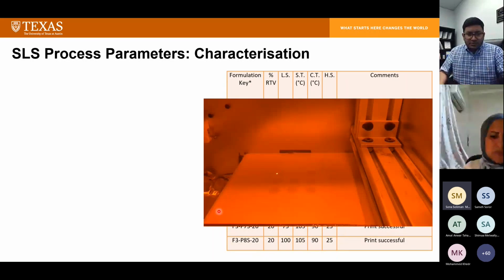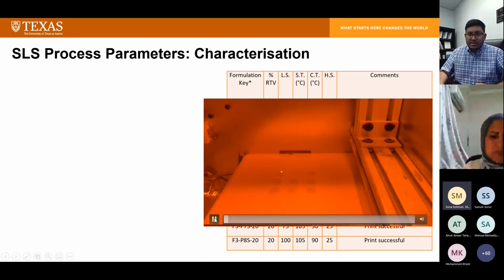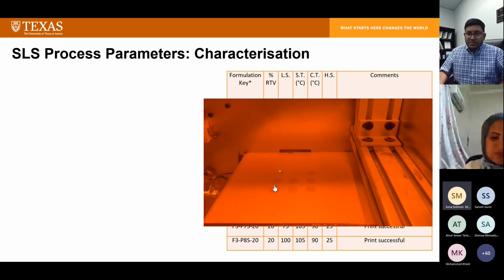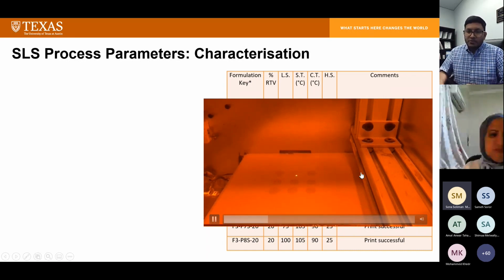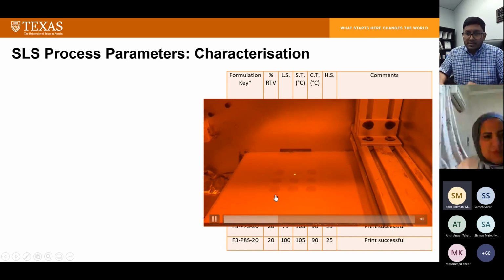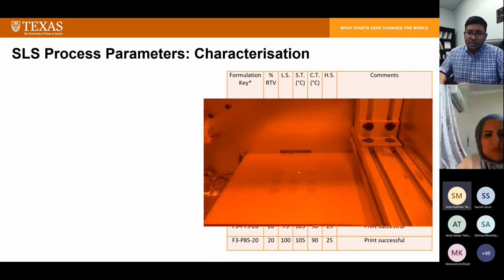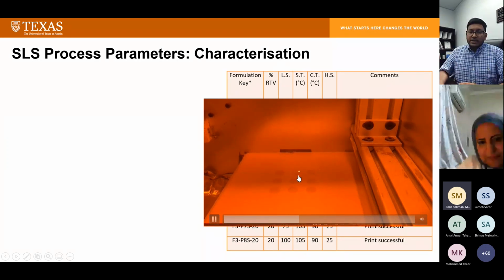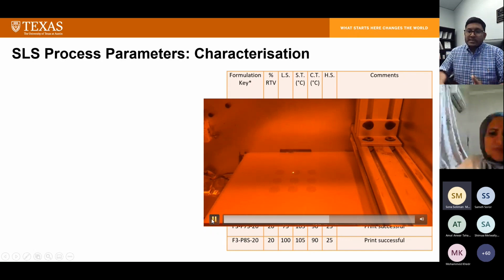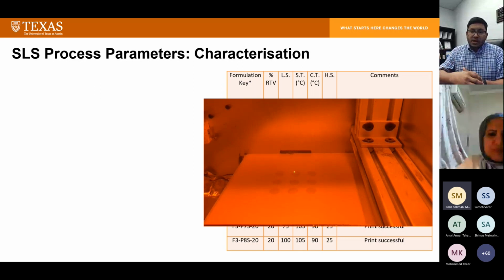And this video shows very quickly how the printing works. As you can see, the laser beam is deposited selectively onto a selective area of powder, layered by this blade over here, and then it fuses the particles layer by layer through the energy produced by the laser. Once the first layer is sintered completely, another successive layer will be deposited onto the previous layer so that the process can continue repeatedly, until we get the final tablet of interest.